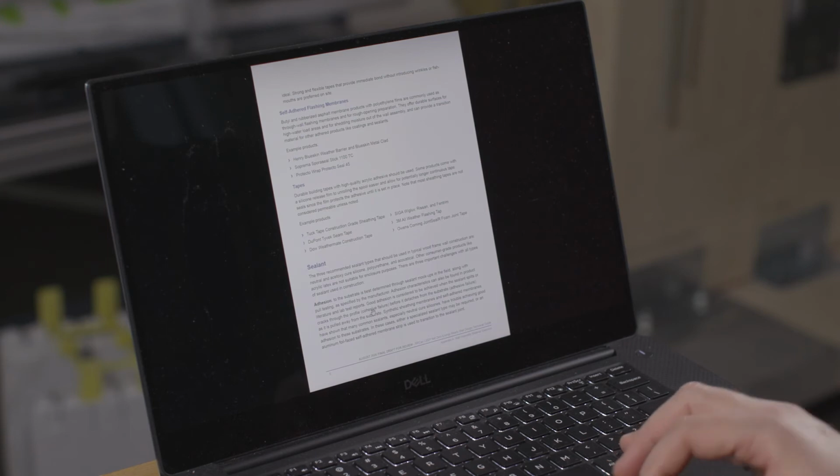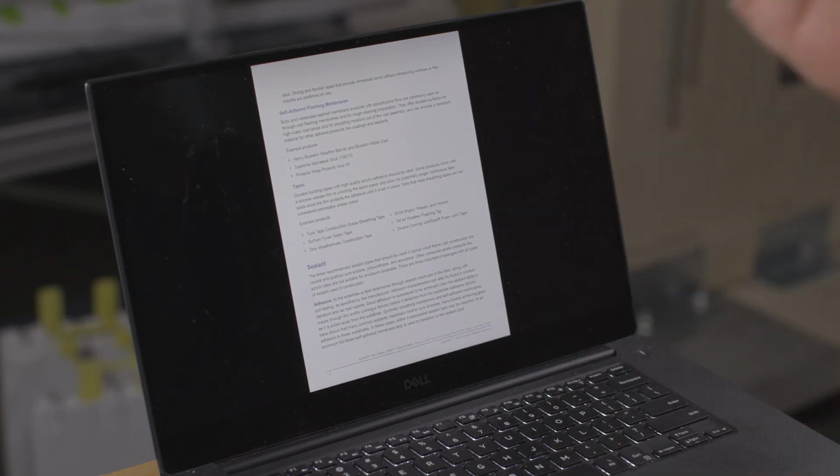Next one is sealants. With sealants, where you're using sealants around window perimeters to seal different transitions, you've got to find a sealant that's going to stick to that substrate. House wraps, which a lot of sealants tie into, are notoriously hard to seal to, and therefore special sealants that have been tailored for house wraps are critical to use. And so what we're looking for here is cohesive adhesion to that substrate. You can often find this from the manufacturer, but often it's just easy to get some of these sealants that you could be using, take a recommended starting point here, and then try them out on your substrate. Build that mock-up, test them out, do the pull testing yourself.